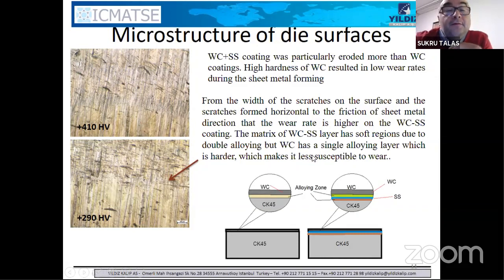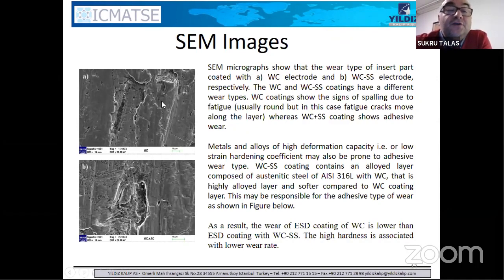As I explained, there are two different zones here. The first zone is the stainless steel CK45 zone, and when we are coating tungsten carbide, another alloying zone is between stainless steel and tungsten carbide. So we have two different alloying zones. The first alloying zone is very soft. Because of this softness, tungsten carbide cracks happen on the surface, and because of the friction, this soft interlayer moves along with the sheet metal. It's still doing the job, obviously, but after a while this surface wore faster than this one. So just coating tungsten carbide on the die surface was better than coating stainless steel and tungsten carbide. So these are the results of die surface defects.